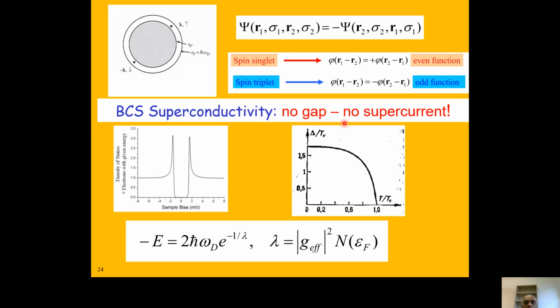In BCS theory, we know you need to have a superconducting gap. If you don't have a superconducting gap, you don't have a supercurrent. Here you can see the density of states versus voltage, which is more like measuring the current. As a function of voltage, you can see there's no supercurrent in this region because you have a gap. After we break the gap, you get this, so this is more like your 2 delta. We know how the superconducting gap depends on temperature, and the gap relates to the critical field here. We know how to calculate all these parameters.